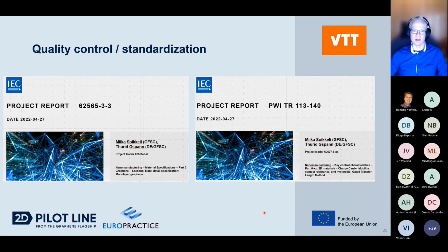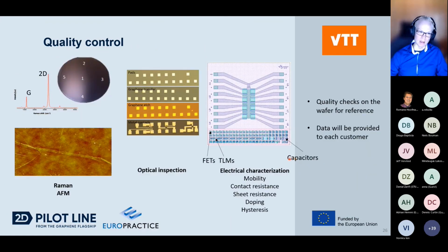Shortly about the quality control and the standardization work. The process has been started in this regard together with the IEC and the Graphene Flagship Standardization Committee. So we are moving forward both on the material characterization side and also on the electrical analysis part. And hopefully this will later be available and utilized as standards in the industry. At the moment, we have quality control including Raman spectroscopy, AFM measurements, and optical measurements during the fabrication, and then most importantly, the electrical characterization, where we are monitoring the electrical parameters: mobility, contact resistance, sheet resistance, doping, and hysteresis of the devices.